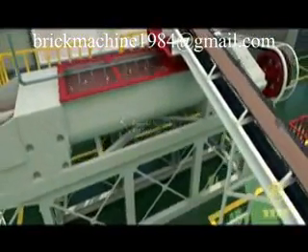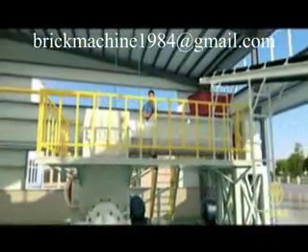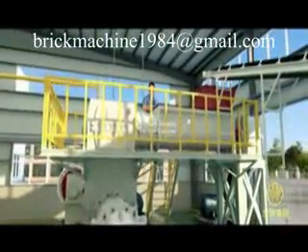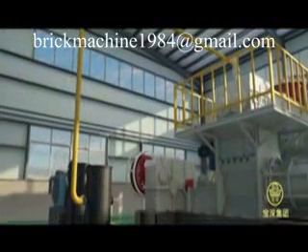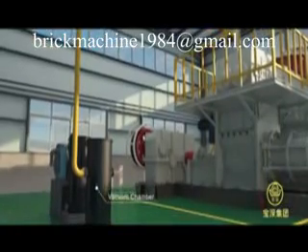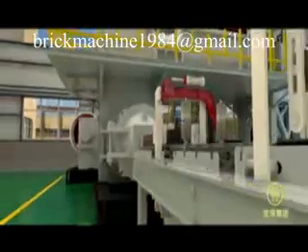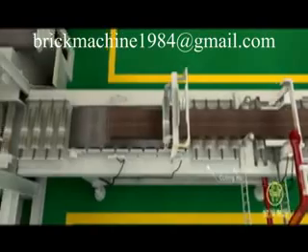Finally, the mixture is sent into a hard shaping vacuum extruder for brick blank making. The hard shaping vacuum extruder consists of top and bottom stages. After blending by the top part of the machine, the mixture is sent into a vacuum chamber for vacuuming. At the bottom stage, powered by a helical reamer, the mixture is shaped into long strips by a mold at the extruder outlet.